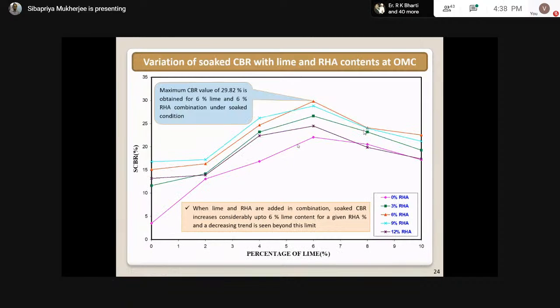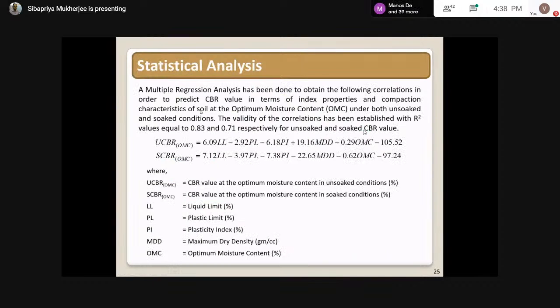Now, this is soaked CBR. When lime and RHA are added in combination, soaked CBR increases up to 6% of lime content for a given RHA, and then it decreases. The maximum CBR we have obtained is 29.82%, for the 6% lime and 6% RHA combination under soaked condition. Then some statistical analysis has been done, and by multiple linear regression method, CBR value, both soaked and unsoaked, has been obtained in terms of LL, PI, MDD, OMC.